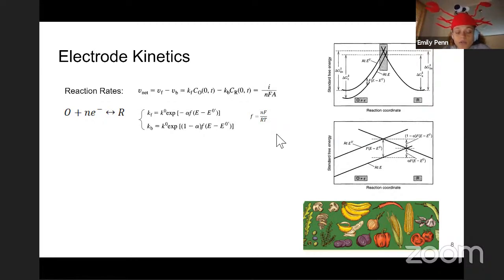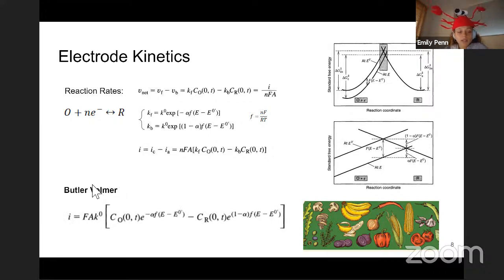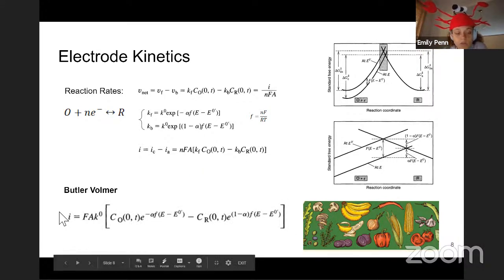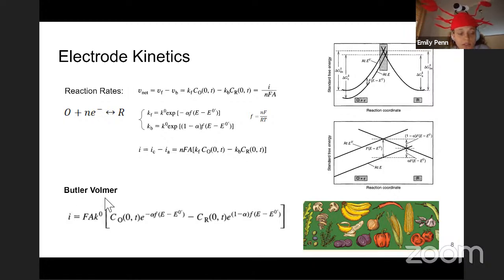Using this Butler-Volmer transition state, semi-empirical treatment, we can determine the rate constants for the forward and reverse reaction. And then using our net current, which we described above, we can know the current for the reaction. This takes us to the Butler-Volmer equation, which we'll use to describe the current at the electrode surface.